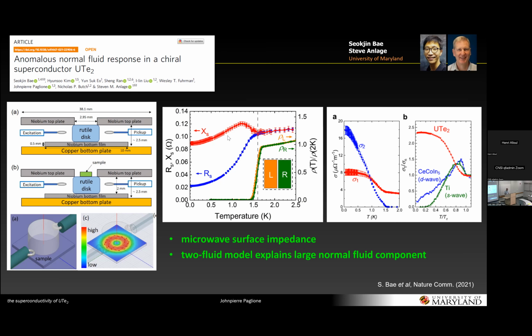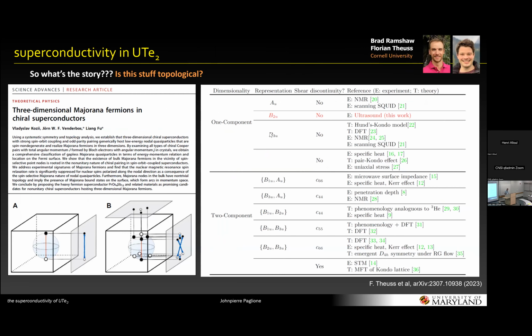And so one interpretation is that there's conducting surface states, and what the origin of those is a good question, but I would venture to say that they are Majorana-like excitations from the bulk order parameter gap structure. Okay, so I'll go on for that. I'd like to make a comment about the surface states. Of course, I don't know anything about the surface states in uranium, and maybe you can call me someone with a hammer that sees everything as a nail. There could be a valence transition at the surface that will produce conductive states on the surface that have nothing to do with topology or very little to do with topology.